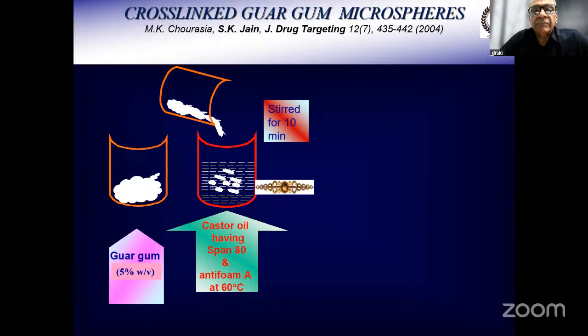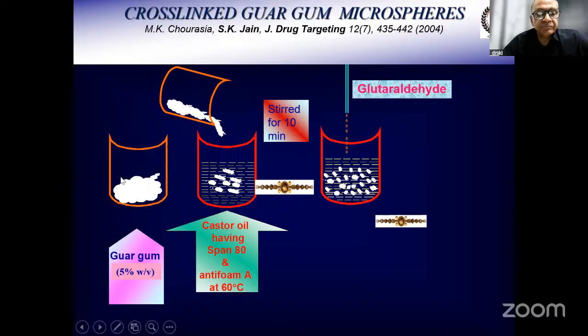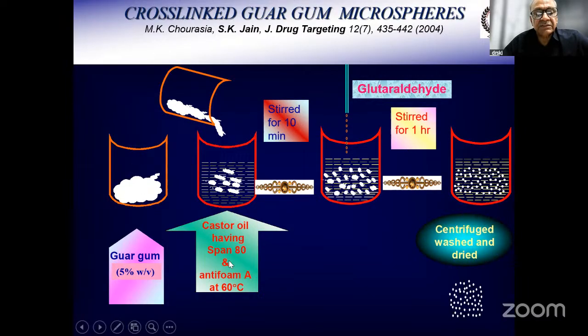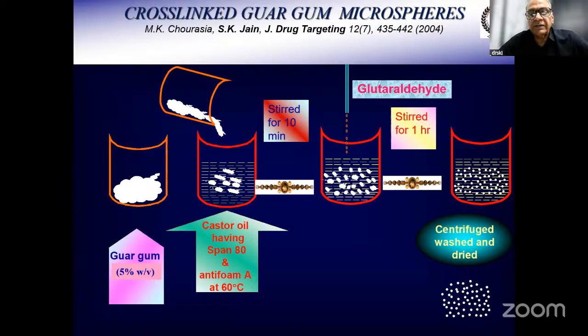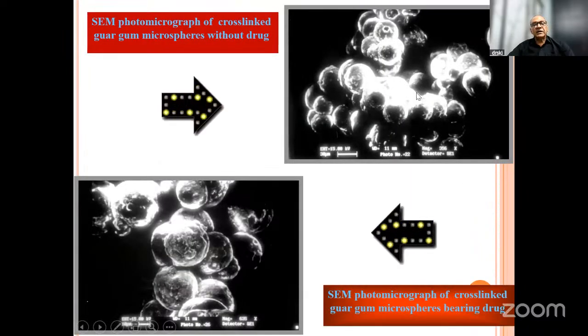So we prepare cross-linked guar gum microspheres. The guar gum solution is dispersed dropwise into castor oil having Span-80 and an anti-foaming agent at 60 degrees centigrade. Stir it for 10 minutes. So we get the dispersion of the guar gum in the castor oil, and the guar gum globules are rigidized by using a cross-linker like glutaraldehyde, toluene-saturated glutaraldehyde, and stirred for a further 1 hour. We get solid rigid guar gum microspheres, which are separated by centrifuge, washed, and can be used. These are the photomicrographs of the guar gum microspheres without drug, and this is guar gum microspheres with drug.